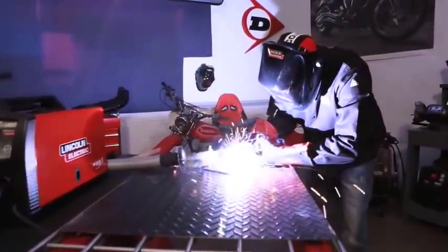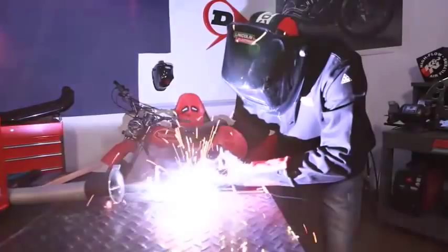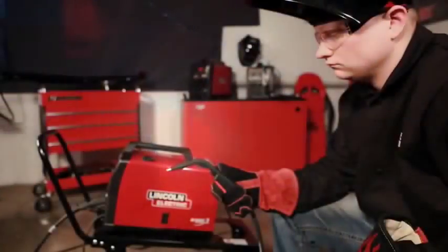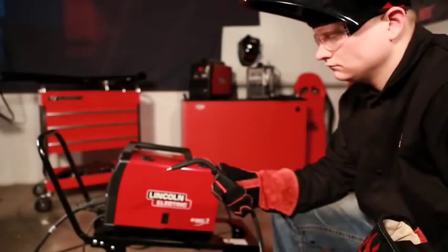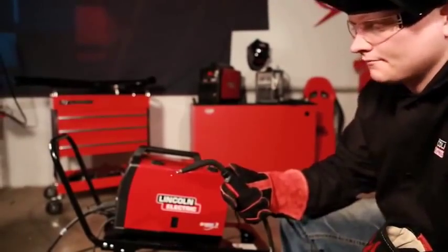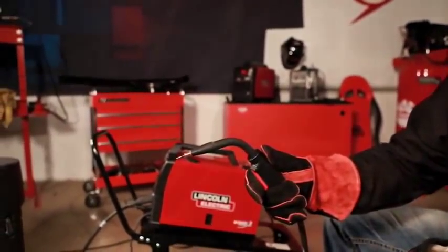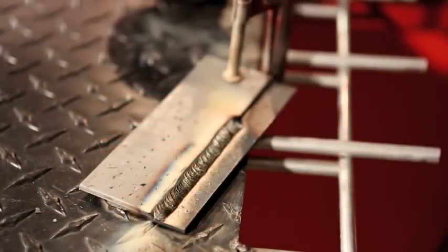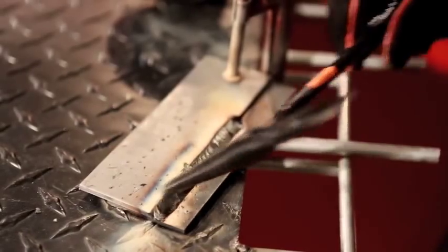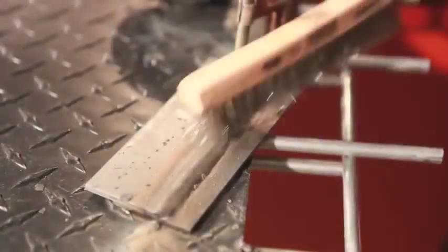Again, to minimize distortion, weld with a backstepping technique. This technique involves evenly distributing the heat by welding in sections. The important thing to watch while welding is not the arc, but the molten puddle behind it. And remember, you should always maintain the proper electrode 1/2 inch stick out beyond the contact tip while Innershield welding. When finished, let the workpiece cool. Remove the slag with your hammer and examine the weld.